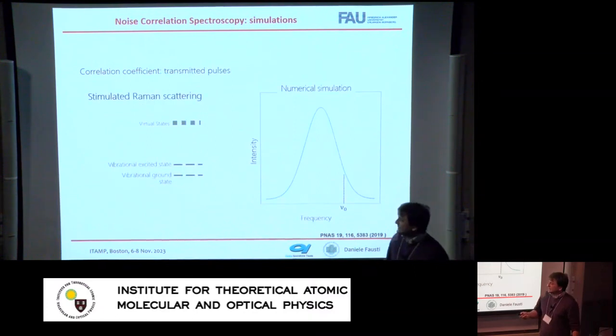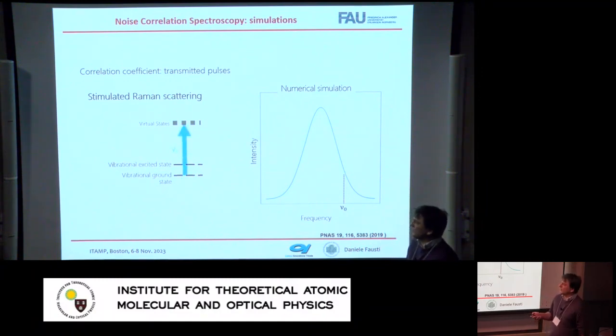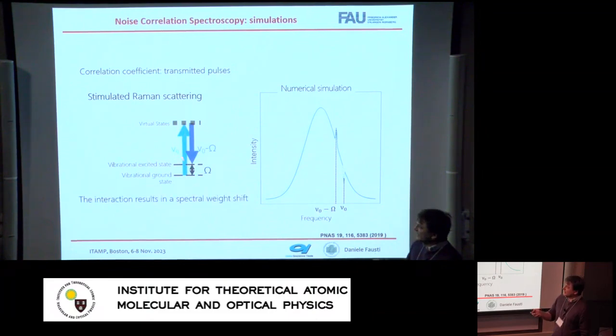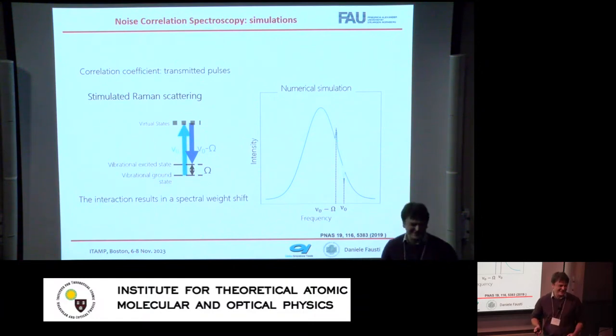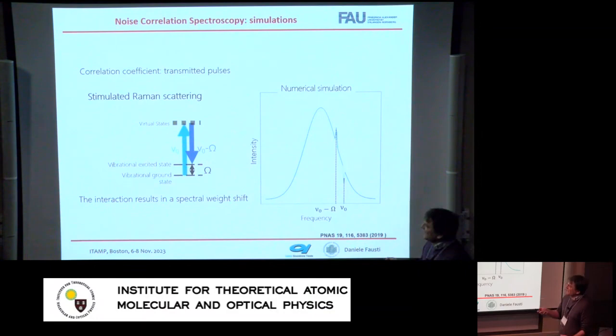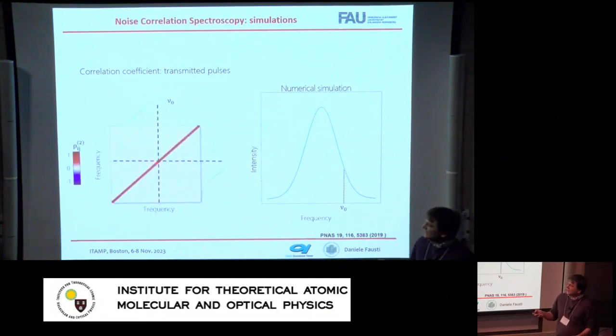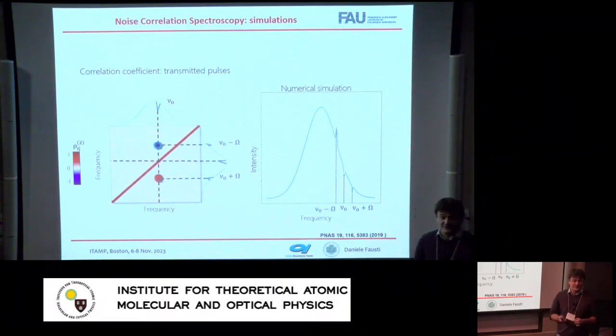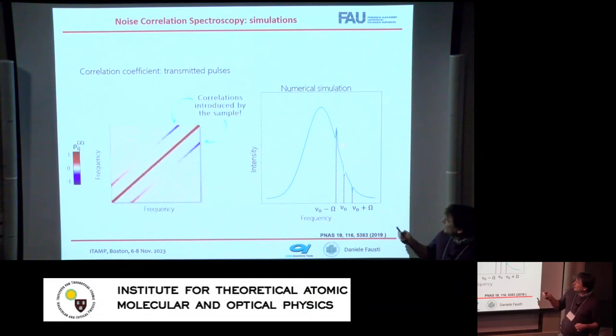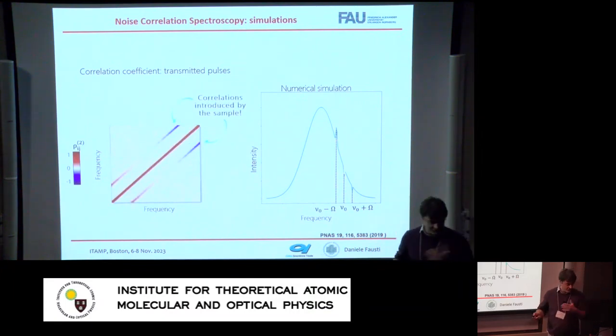Why is this interesting? Well, as I said, the target for us is the non-equilibrium response, which is the nonlinear process in the system. And if you think about the nonlinear process, for instance, as impulsive stimulated Raman, which destroys a photon in one frequency component and creates a photon in another frequency component, which is related to the first one by the frequency of the boson which mediated the scattering process, then I can think that if I start from frequency uncorrelated fluctuations and I allow this scattering process to happen, I will introduce correlations between different spectral components. Of course, because if a photon disappears in one frequency component, it has to appear in another frequency component, which is big omega apart.